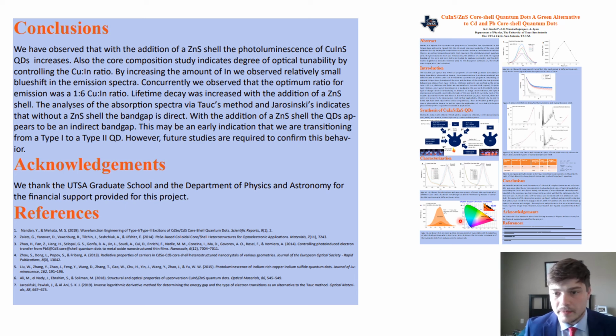We demonstrated that there is an enhancement in your photoluminescent spectra just by adding the zinc shell. We showed that there is an optimal ratio to synthesize these with, and from our experiments under our experimental conditions, the 1:6 ratio was the optimal ratio that gave us the best photoluminescence. We then took the lifetime decay measurements for the core and core shell.